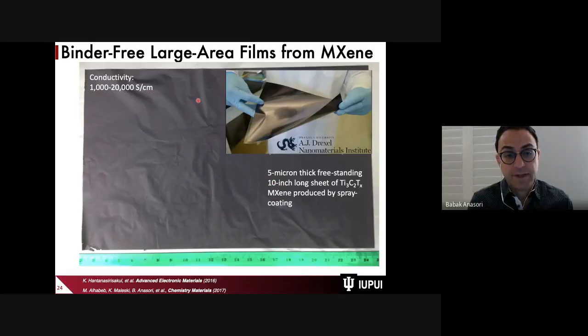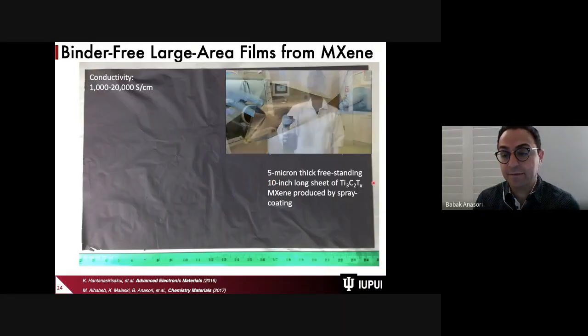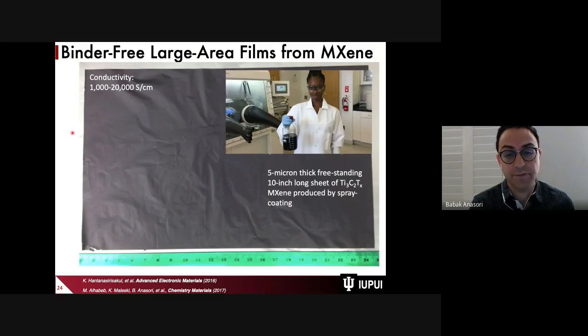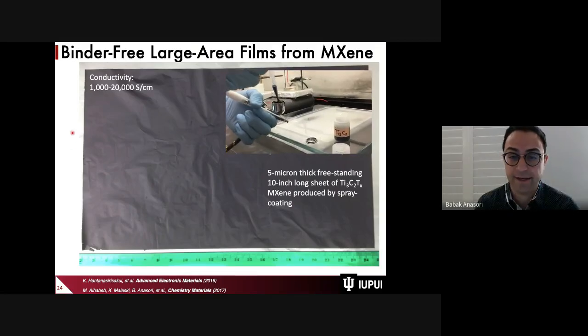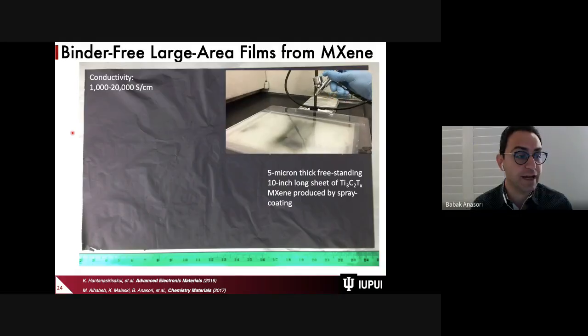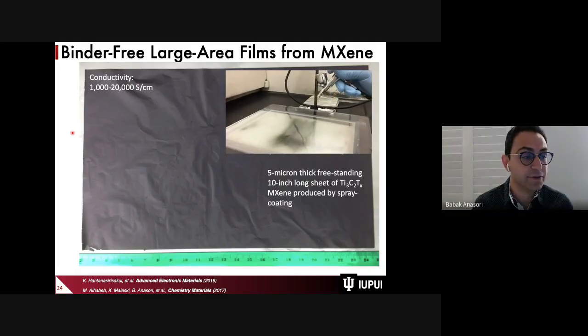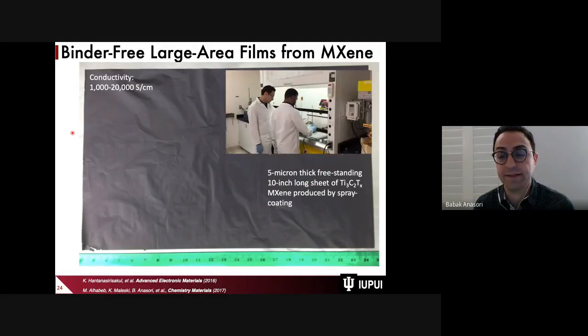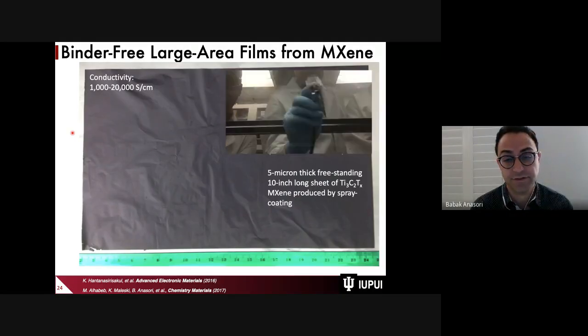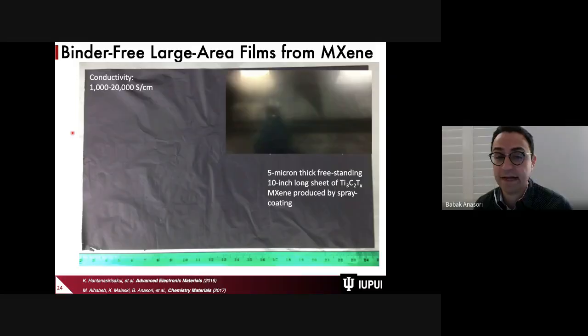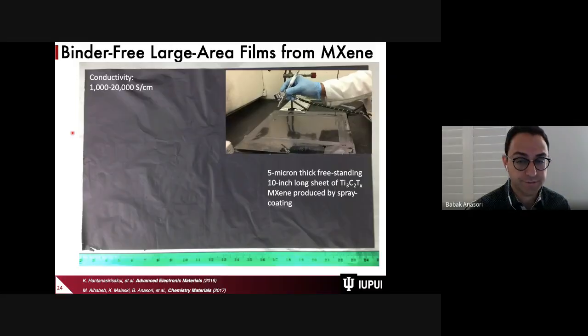Again, here is a paper size film that has been sprayed using this solution. And here's a movie showing how just by simple spraying, we can make these films. When we make it out of these nanostructures, they can easily stick to the surfaces, and they give a very high conductivity of 1,000 to 20,000 Siemens per centimeter.